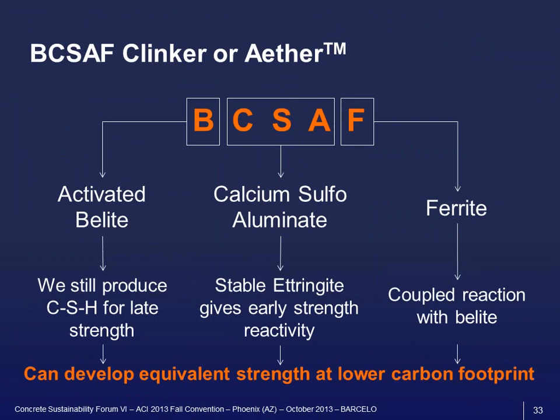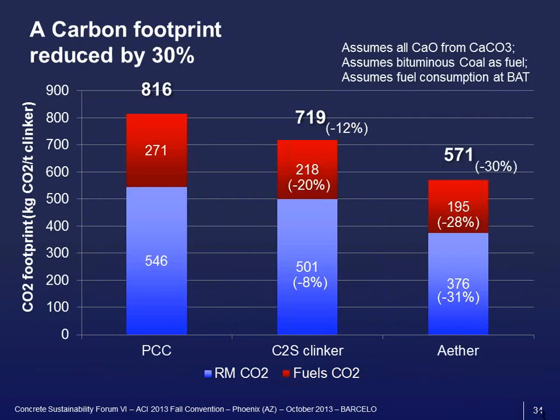How much lower? So we've seen that ordinary cement is at 816. With the theoretical C2S, we are down by 12%. With this approach, we are down by 30%. And what's very important here, you can see that we significantly reduce the CO2 coming from the raw materials, as well as reducing the CO2 coming from the fuels.